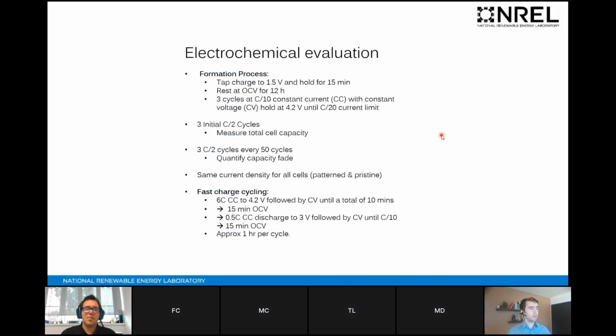So for electrochemical evaluation, this was the protocol. We conducted a formation process. We then did initial C/2 cycles to measure the total cell capacity. And then every 50 cycles, we repeated that C/2 cycle to quantify the capacity fade. And the fast charging conditions were 6C constant current to 4.2 volts, followed by constant voltage until a total of 10 minutes, followed by 15 minutes of open circuit, followed by 0.5C constant current discharge to 3 volts, followed by constant voltage to C/10, and then a 15-minute open circuit again after that.